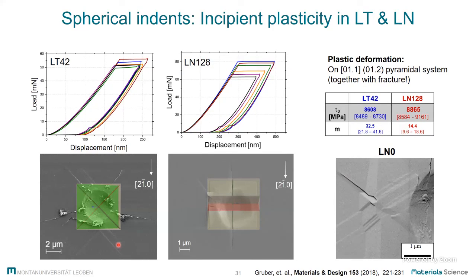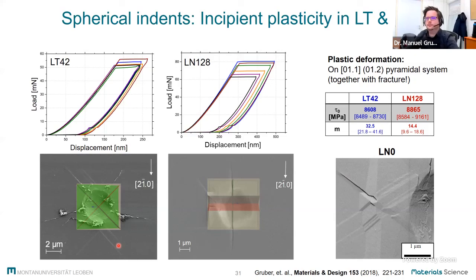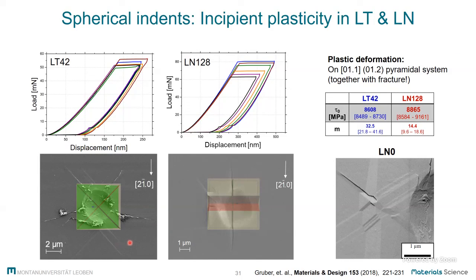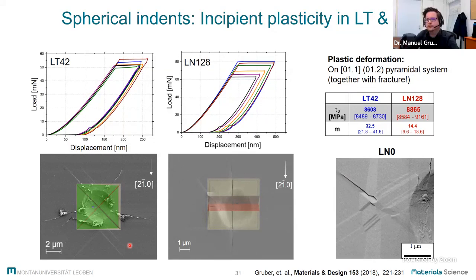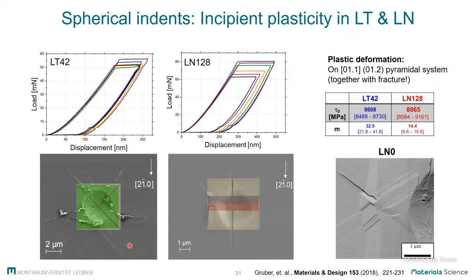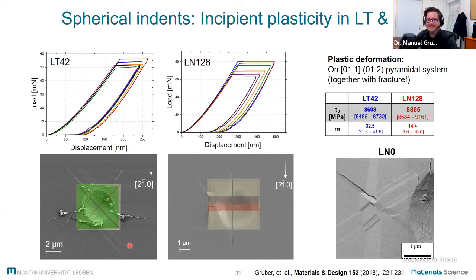I checked the lithium niobate and it needs to go up to 1100 degrees C to completely induce the plastic deformation without cracking. But with the small particles, maybe the temperature could be lower because we can induce much higher local shear stress, as you showed here, actually, for the nanoindentation. But that's an educated guess for now. Thanks. Okay, thanks a lot.